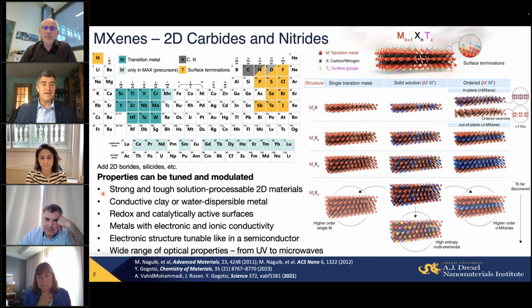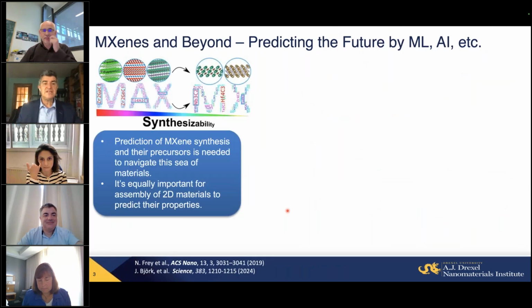What is important? Carbides and nitrides are very strong. Actually, they're stronger than other solution-processable 2D materials here. And they have metallic conductivity. Without surface termination, all of them would be metals. Surface termination can open a band gap in some of them, but again, they're metals, but they also have ionic conductivity between the layers because of these terminated groups here. And of course, a variety of properties.